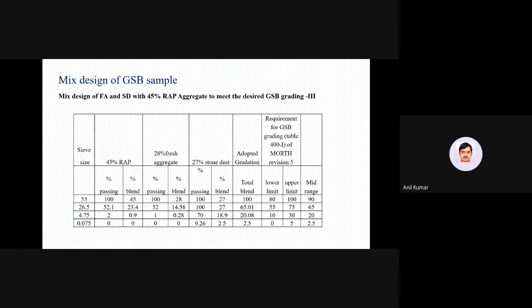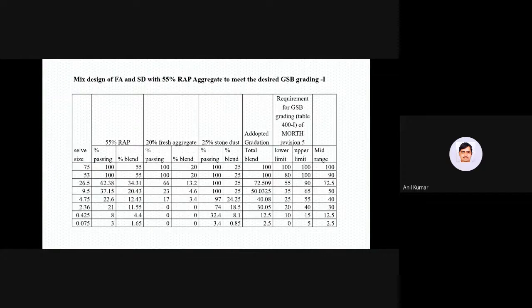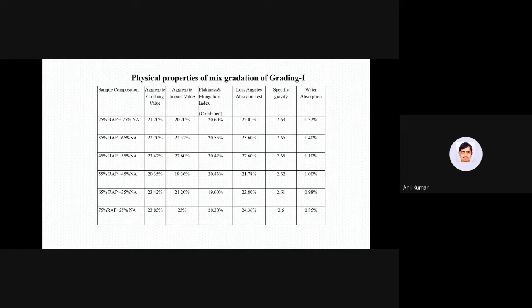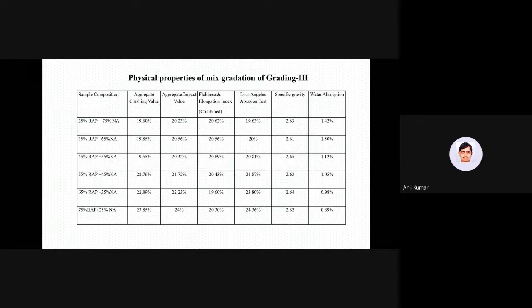Then these are the mix designs of GSB grading 3 and GSB grading 1 as per MoRTH classification. Then these are the physical properties of the mixed gradation of grading 1, that is the filter layer. From this table we can say that the test results indicate the materials show good results when the RAP is 55% and the fresh aggregate is 45%. All the properties are showing the minimum values compared to other proportions. Then these are the physical properties of gradation 3, and the best result was at 55% RAP and 45% fresh aggregate.